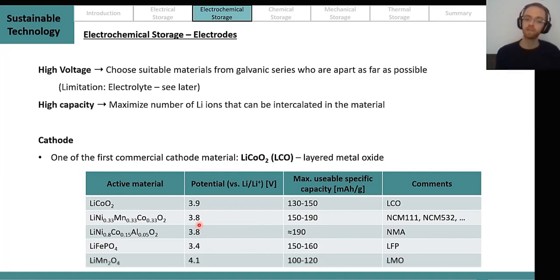So now, depending on this active material, you will have a different potential versus lithium. So this is basically your cell potential, which you will ultimately have. And it gives you a different maximum usable specific capacity. So relative to weight, there are different amounts of lithium which can be extracted or inserted in the corresponding structures. So the first commercial material, as I already teased you in the header, is lithium cobalt oxide, which has a potential of 3.9 volts, a usable capacity of 130 to 150 milliamp hours per gram, and it's typically abbreviated as LCO.